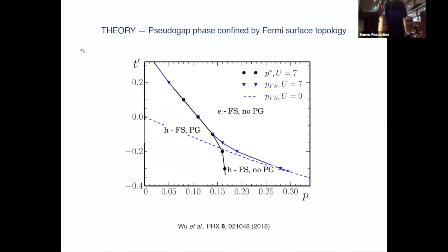In other words, the Van Hove point actually is affected strongly by interaction. And what they found is that by looking at where the pseudogap happens, indeed, it always happens below the Van Hove point. So they also arrive at the same inequality. In other words, it appears that you cannot have a pseudogap if you have an electron-like Fermi surface, which doesn't cut the antiferromagnetic zone boundary.